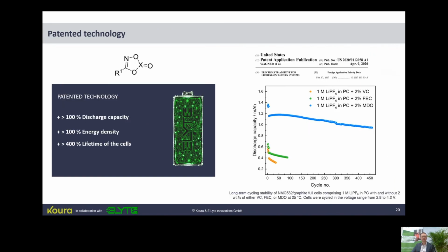Yeah, as I said in the working principle of the lithium-ion battery, we are also focusing on SEI additives because I showed the importance of these additives to the field and to the lithium-ion battery. And there, of course, I would like to show you one of our patents. So we applied for a patent with a carbonate derivative, which is substituted with a nitrogen atom. And the rest here, of course, gives us multiple possibilities to substitute, and also, for instance, with fluorine-containing compounds.